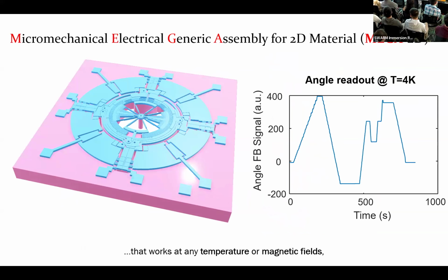And now, because we want to study these 2D materials, one of the things we want to be able to achieve is to operate this device at any temperature or magnetic field, because these are things that are often required to see those scientific discoveries in these materials. So we actually tested these devices down to 4 Kelvin, and it works perfectly fine because these are electrostatic devices, and there's nothing really limiting their operating temperature.